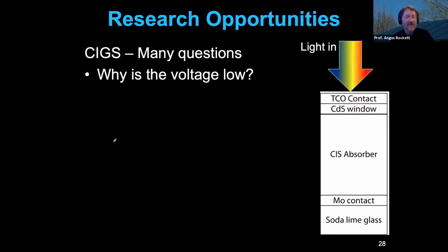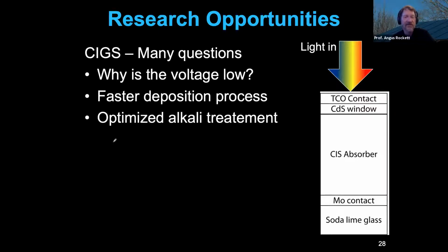In these materials, the voltage is again low relative to where it should be because there's too much recombination of carriers in the device. We'd like a faster deposition process, and I mentioned the fact that you need to have very little time in an expensive process. And so we need a faster way of depositing the material. I'll show you an example of how my group attacked that problem.